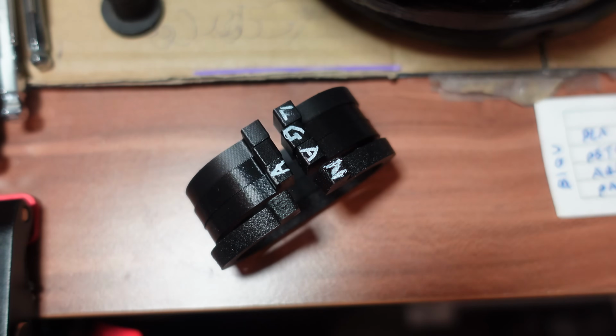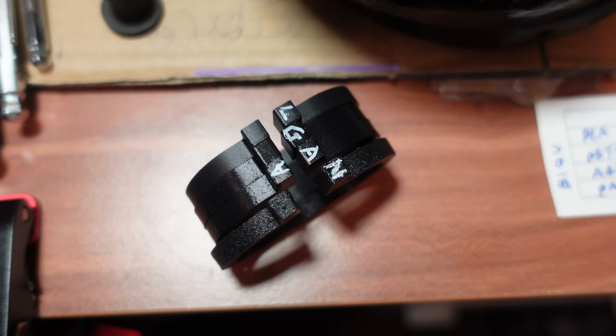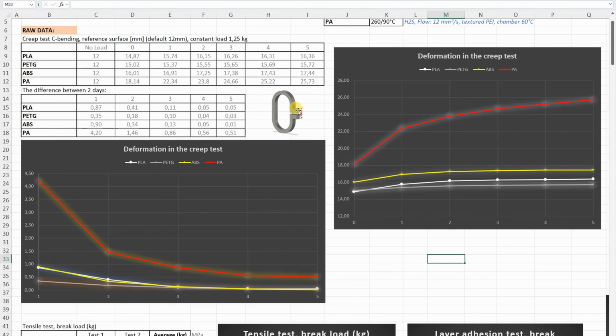And their deformation after 5 minutes. On this graph we can see the distance between two reference surfaces, and of course biggest deformation is on the nylon, and the smaller, well, depends. Look at this initial deformation, smallest is on the PLA, but with the more creeping it has more deformation later.